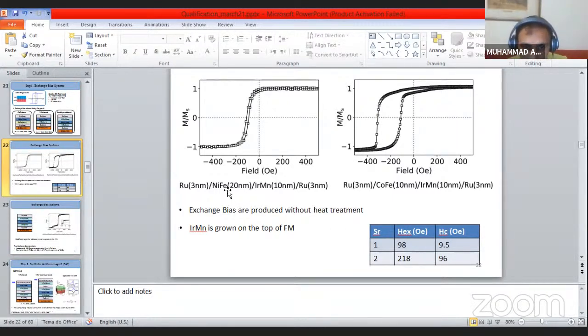Nickel iron is considered a soft ferromagnet. It has low coercivity. You can see a soft ferromagnet always has a low coercivity. This kind of system has applications in switching, while cobalt iron is a hard ferromagnet. A hard ferromagnet always has a higher coercivity. This kind of exchange bias can be used as a memory element, because for reading and writing we need a higher coercivity, so that during the operation it will not change its polarity and will not demagnetize.